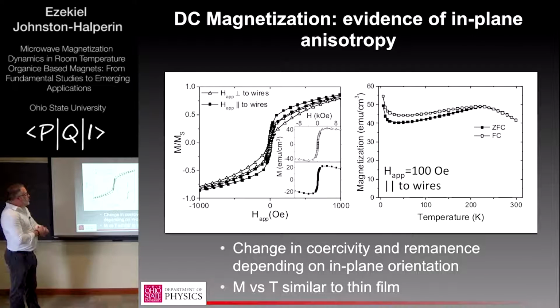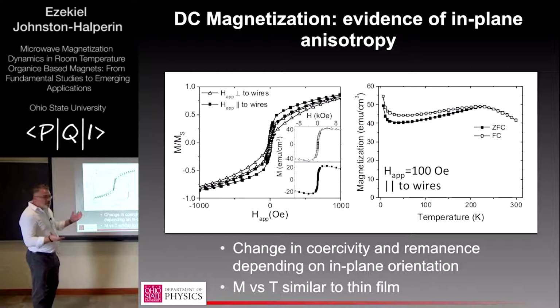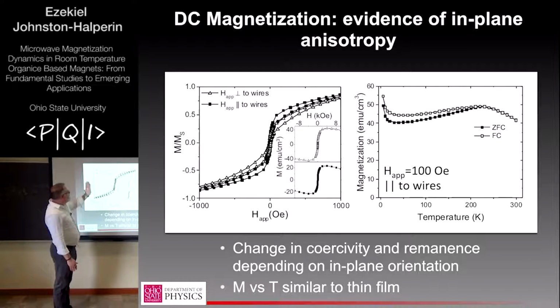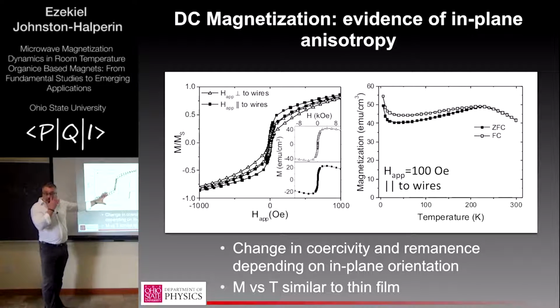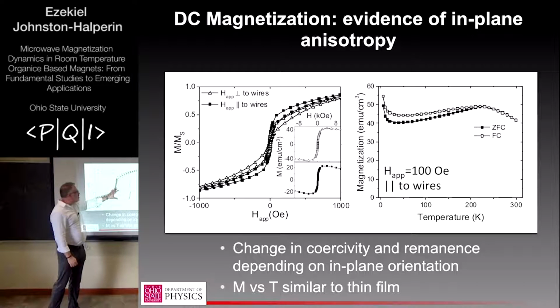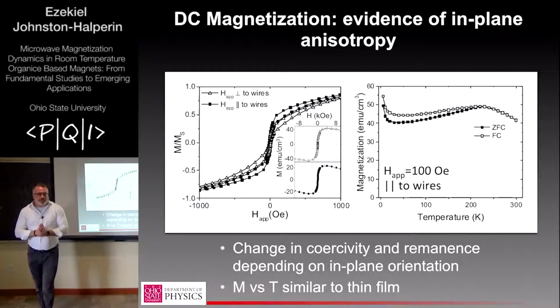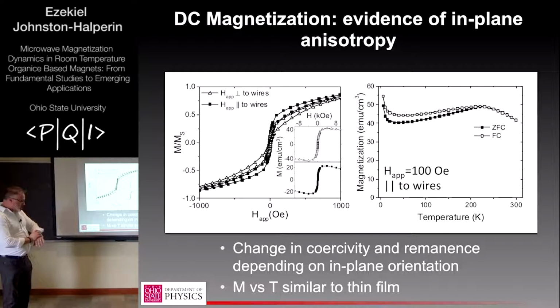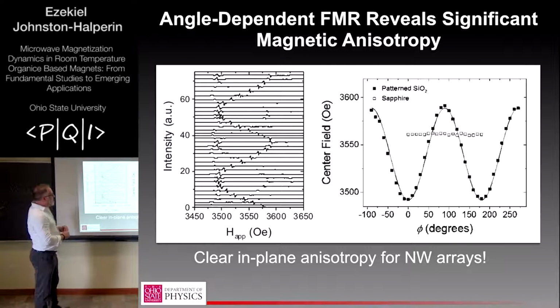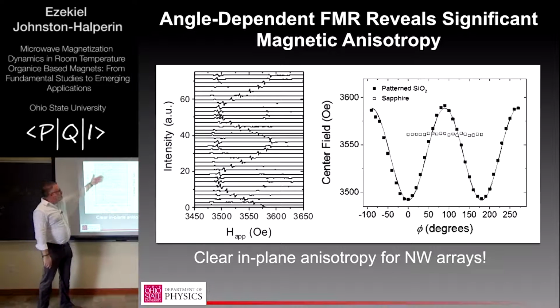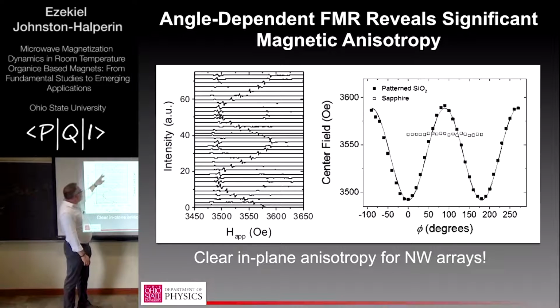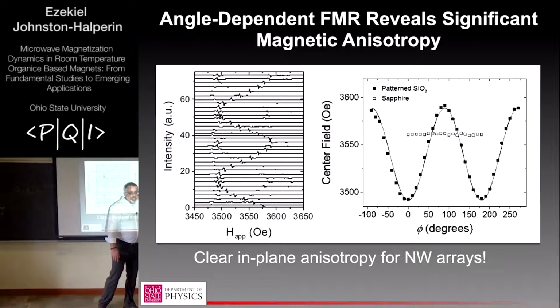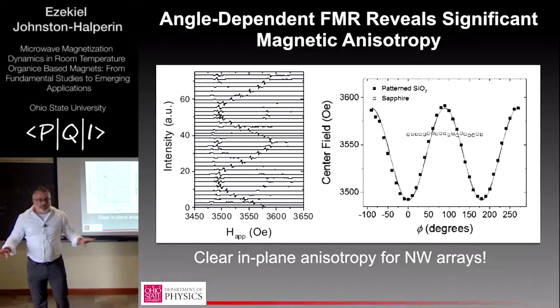we thought. So then we tried to look at the anisotropy, measuring DC magnetization, parallel and perpendicular. This is not really the best way to measure magnetic anisotropy. We can see that those two curves are different, but extracting parameters from that is challenging. So what we did was we went back to FMR and we varied the in-plane angle. So that's this waterfall plot here. You can see this very clear sinusoidal oscillation, which we fit and extract here to the black data points. For comparison, the open squares are for a continuous thin film.